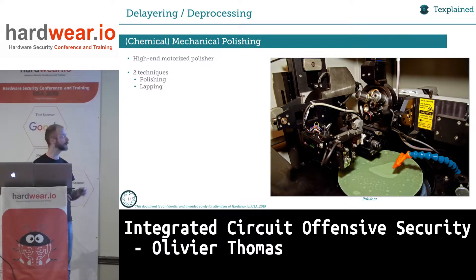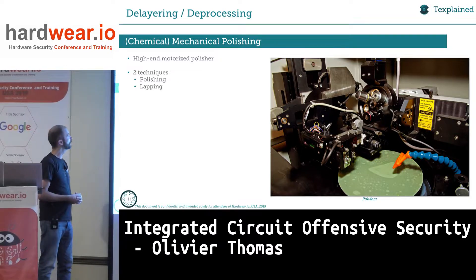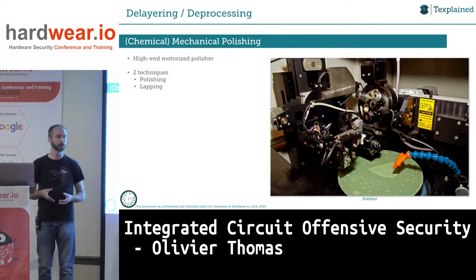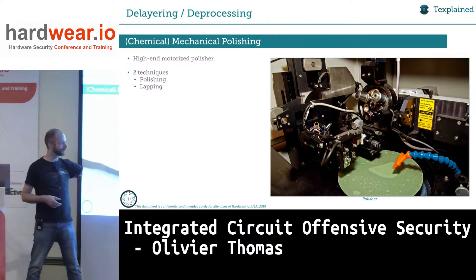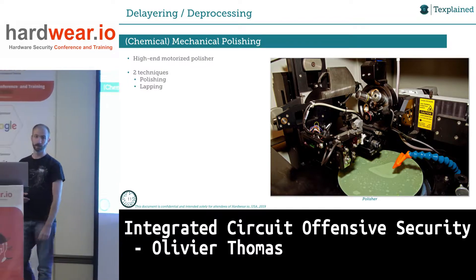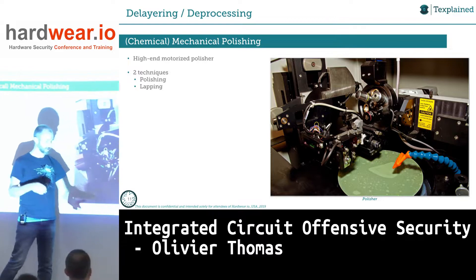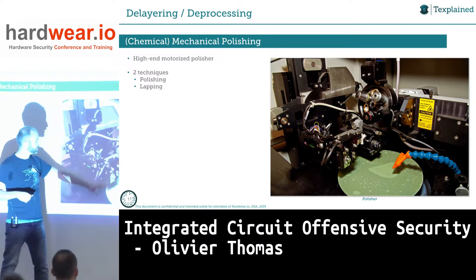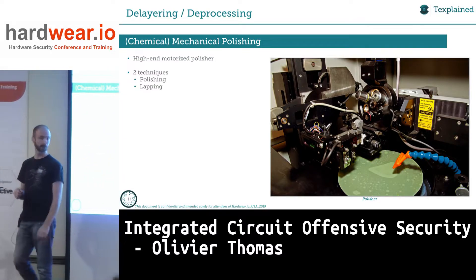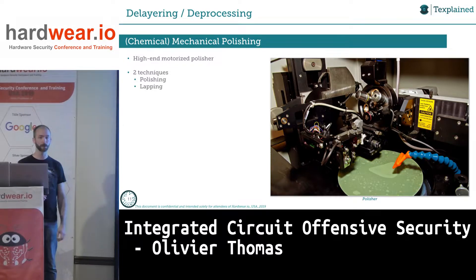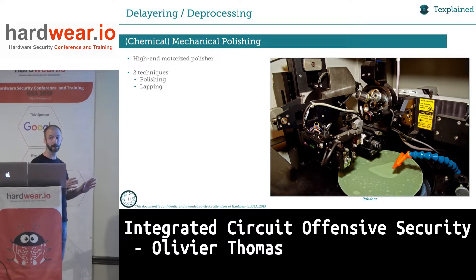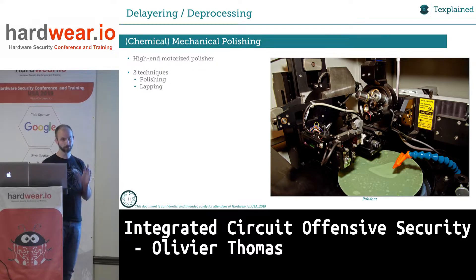The idea is really to combine different techniques: wet chemicals, dry chemicals, and also chemical mechanical polishing — CMP. For me it's mechanical polishing only since I'm not the chip vendor and I have no idea of the materials used. This is the machine we use — a polisher with diamond-particle-coated discs. It has an optical microscope and a five-axis arm. It's super precise; you can polish chips below 90 nanometers. The key is to mix all the techniques.